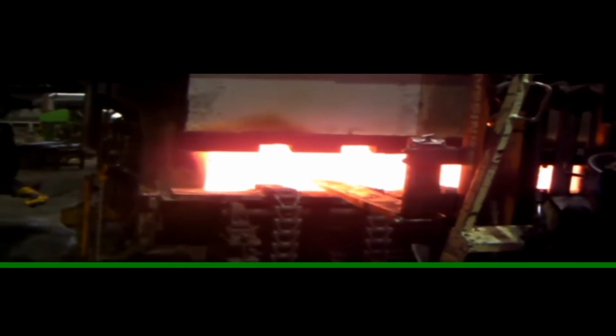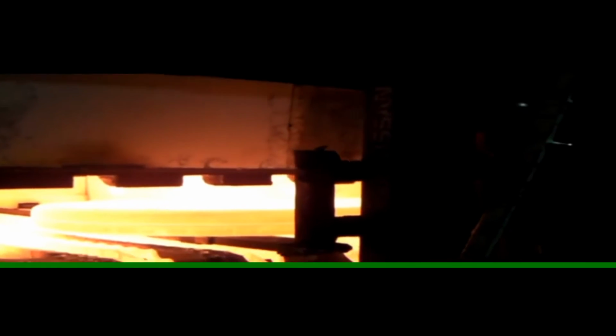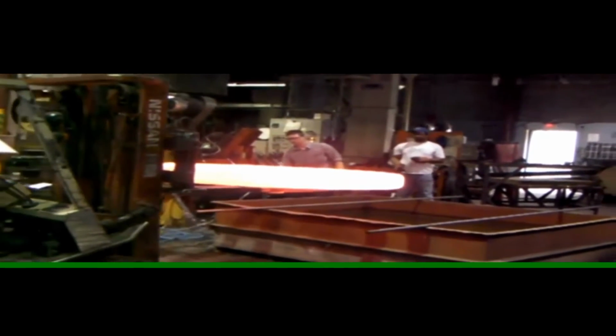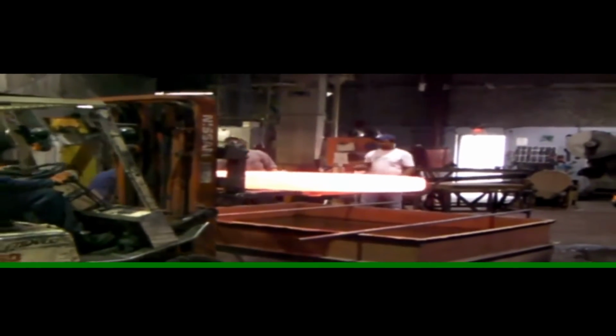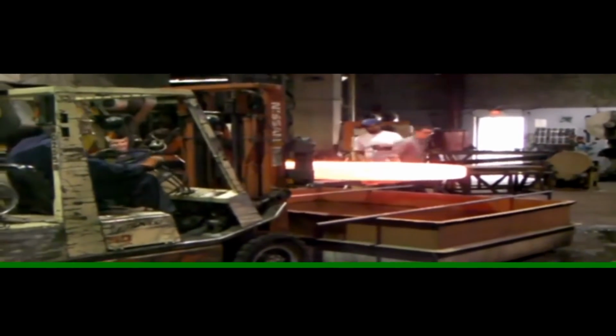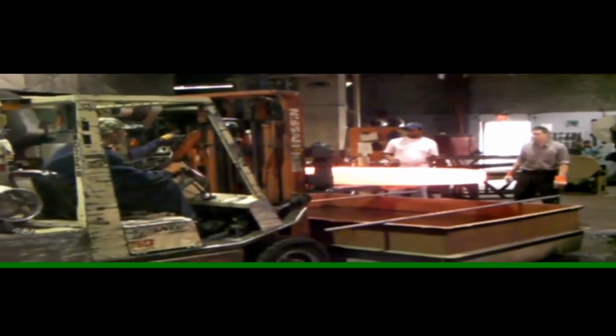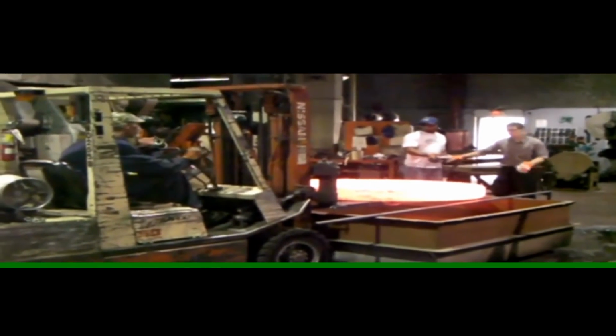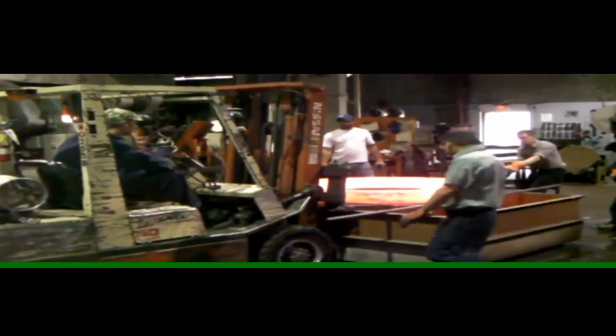After soaking it at an elevated temperature for a period of time, the complete austenite will be developed in the microstructure and it will be removed from that elevated temperature. So during liquid quenching, the temperature of this metal must be rapidly cooled, and this can be done by dropping it into a liquid in order to transform its microstructure from austenite to martensite. So you will see in a few seconds that the quenching process will be performed to this steel.